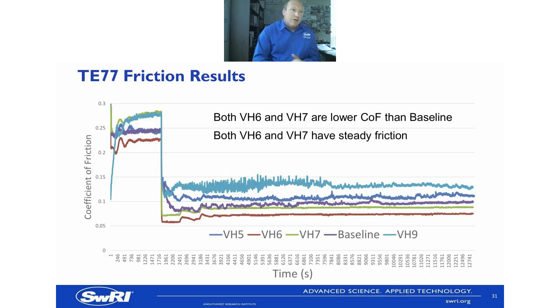You can see that the purple is the baseline, and we have VH5, 6, 7, and 9, which are the 4 coatings that we tried. You can see that we have 2 which are actually higher friction than the baseline, so that's an undesirable outcome in this situation. But they're also quite noisy, and you can see we have 2 coatings that have run in nicely and are lower friction and actually much less friction noise in there as well, which is highly beneficial and what we're looking for. So we're now just going to look at VH6 and 7 moving forward, because we've already discounted 5 and 9.